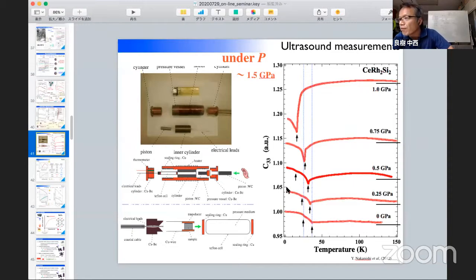But please take a look at the left panel. This is the temperature dependence of the elastic constant of cerium, a rare earth, cerium rhodium 2 silicon 2. At ambient pressure, the elastic constant stays almost constant independent of temperature, but it shows this kind of step-like anomaly due to magnetic transition, successive transitions. But under applied pressure, as you can see, the elastic softening gradually grows, and at a pressure of 1 GPa, we observe pronounced elastic softening as we see in the other rare earth systems. So we call it pressure-induced elastic softening, which is also the opposite behavior at room temperature.